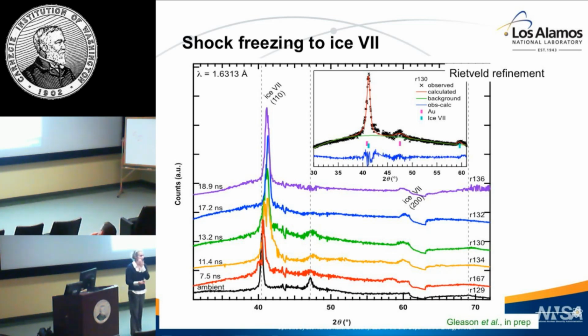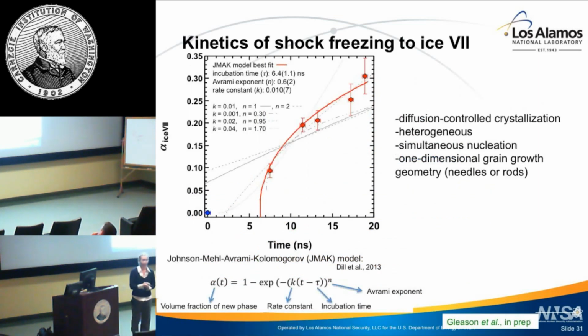So we have this methodology that I've developed using this embedded gold layer to pull out the phase fraction of the crystalline ice. And I have this fit. From the fit, I'm finding that the exponent is very small. This is unusual, okay? It's not common. The mechanism proposed in a lot of the literature is something like one-dimensional rods or pencil-like crystallites of ice VII, perhaps. But this is a very qualitative perspective. This is probably not right, but this is the best we can do in understanding how to frame our kinetics data in the context of classical nucleation theory. So it's a good first step. Is this absolutely the correct answer? I don't know yet, but this is where we're going.